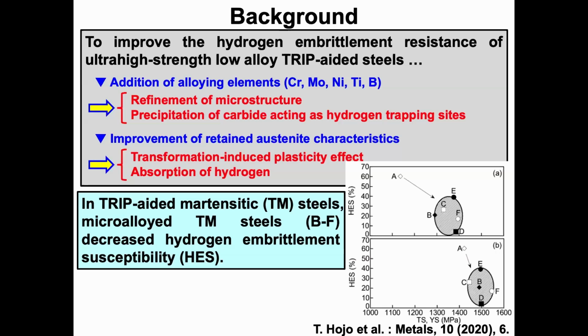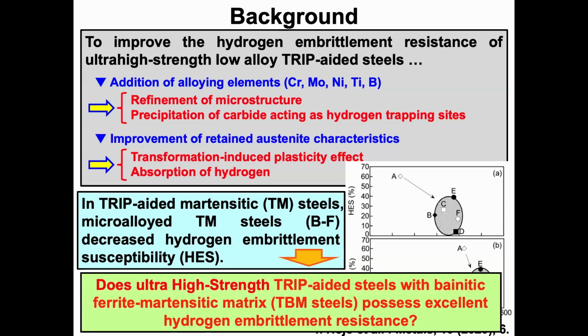About the previous report, in the TRIP-aided martensitic steels, TM steels, microalloyed TM steels decrease the hydrogen embrittlement susceptibility. So it is expected that the hydrogen embrittlement resistance may be enhanced by the partial replacement of the martensite with bainitic ferrite, because bainite or bainitic ferrite possesses excellent resistance to hydrogen embrittlement.